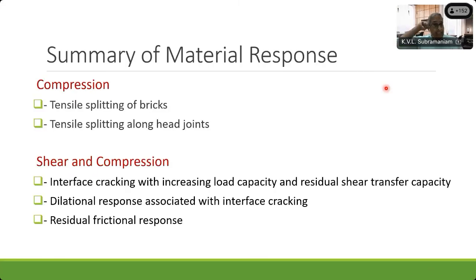So in summary, when I talk about masonry, I have a tensile splitting of bricks that we see. That's because of the biaxial tension state that is produced in the mortar. And we see tensile splitting along the head joints. In the mortar, under shear and compression, we see interface cracking, which happens between the brick and the mortar interface. It's a dilational response, which means as the shear crack forms, there's expansion that takes place. And the final resistance is given by the residual frictional resistance between the two materials once the crack is formed.